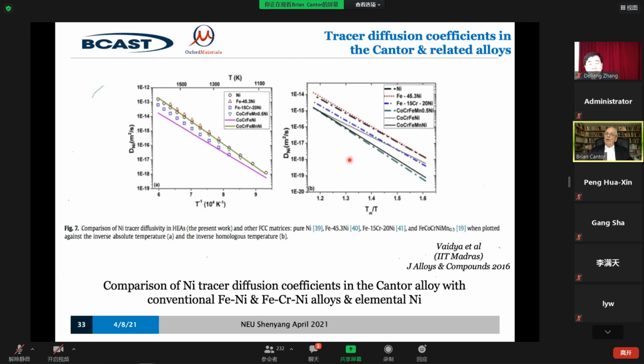Now that's very important because it means that the Cantor alloys are very resistant to degradation in different ways. They're resistant to degradation at high temperature, because the diffusion is slower. They don't decompose so easily and lose their structure. They're resistant to degradation by corrosion and oxidation because the atoms can't migrate to the surface so easily. And they're resistant to degradation by radiation. So they're radiation damage resistant because the damage that's caused is fixed in place and doesn't migrate around to create pores, which is the real problem when you get radiation damage. So this is a very important effect, the diffusion effect.